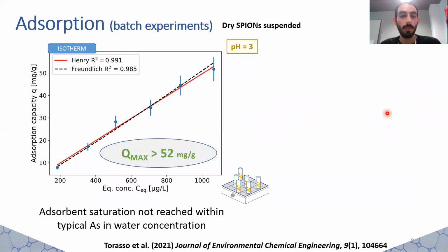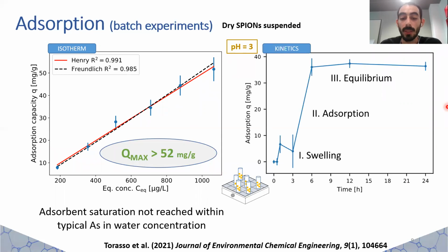With this material, we performed batch adsorption experiments. The adsorption isotherm shows the typical linear behavior for low equilibrium concentrations, and saturation of the adsorbent was not reached in the studied range, corresponding to typical arsenic concentrations in contaminated water. We conclude that the maximum adsorption capacity of the nanoparticles was at least 52 milligrams of arsenic per gram of magnetite. An interesting behavior was observed in kinetic experiments, where we can see a delay before actual adsorption begins. This can be explained by the swelling of the membrane.